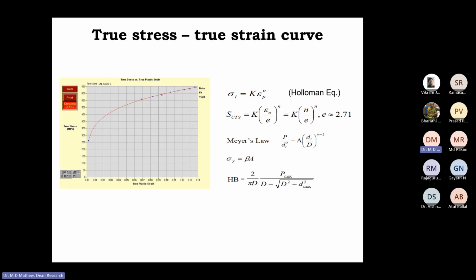So now that you have got the true stress and true strain values, you have many constitutive equations by which you can correlate the true stress, true strain values. Hollomon equation is a very popular one. It says that the true stress sigma T is equal to a constant K into the true plastic strain to the power of N, which is the strain hardening exponent. So this is the true stress, true strain curve that is generated from the load versus depth data that we have seen earlier. And by analyzing the true stress, true strain curve, we'll be able to get what is the UTS of the material through this relationship. UTS is equal to the strength coefficient K into epsilon U divided by e to the power of N, where e is a constant for the materials.